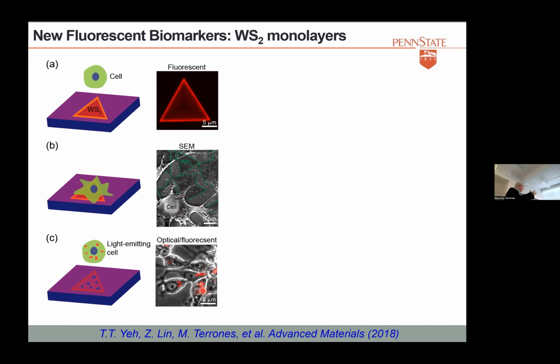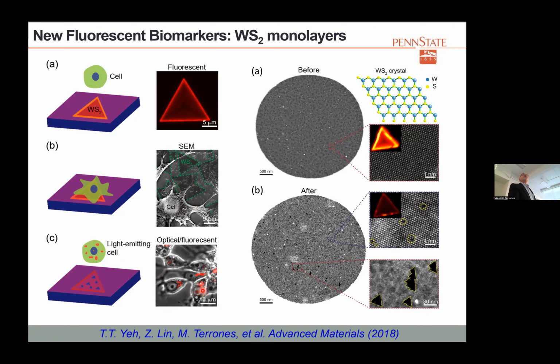But it was interesting because we asked, okay, how much material, how is the ingestion happening, and then we did some TEM and PL before and after digestion. So this is the PL. This is the pristine material, and this is after the cell has ingested the material. We have more extended defects that have happened, right? And then you have these cells that sort of tear apart these fragments, which are very tiny, right? The scale bar is 30 nanometers. So these are triangular ones, like eating Doritos, right?